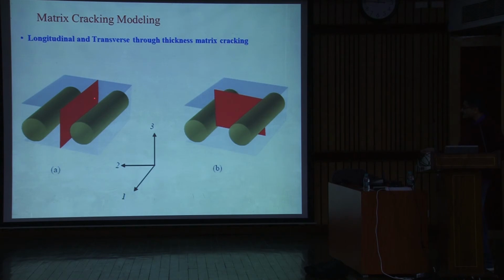So these cracks develop easily, whereas these cracks do not develop easily, because when you are applying the load in the fiber direction, most of the load is taken care of by the fiber. So the fiber fails first in this case, and then the matrix, so there is very little chance to develop this kind of cracks. Whereas if you are applying the load perpendicular to the fiber, it is very easy to develop these cracks. This is the prominent matrix cracking phenomenon seen in the unidirectional fiber composite.